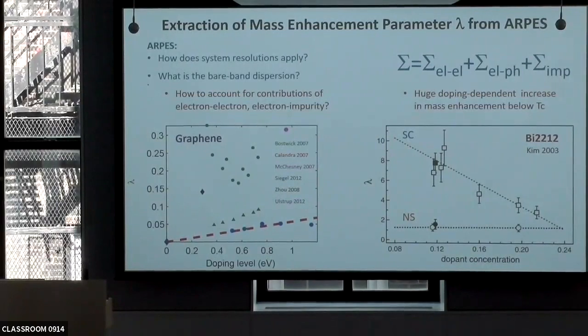And I would attribute the issue here to two aspects. Anytime you do this kind of analysis of a lambda, you're assuming a bare band. You're basically imposing some behavior for the bare band. And then, people, at least you have shown that you go way beyond that. But what experimentalists often do, once they have established a bare band, is write a self-energy as an additive contribution from all possible terms: electron-electron scattering, electron-phonon, impurities. But of course, this is not correct. Really, you should have a well-defined Hamiltonian that contains all of your interactions. Then you would go and calculate your self-energy, and then from that, you could try to extract some quantities. So this is what happens, in my opinion, when you look at electron-phonon coupling this way: here is a dispersion, let me put a linear band through it, look at the difference between the data and the band, and from that infer what the self-energies are.